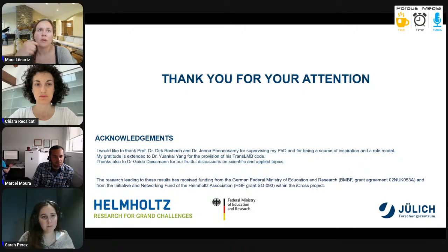Of course, I did more than those 2 experiments, and some experiments failed because it was detaching from the glass, and then you couldn't see really sharp lines from the glass. So it was limited in time, the total time of the experiment, but also well controlled by continuous Raman mapping. But in the experiment that you have shown, the pillars, are they always PDMS or is it glass? So inside where it was growing, there was a solution, and the other one was just glass. So you had both types there? Yeah. Okay.